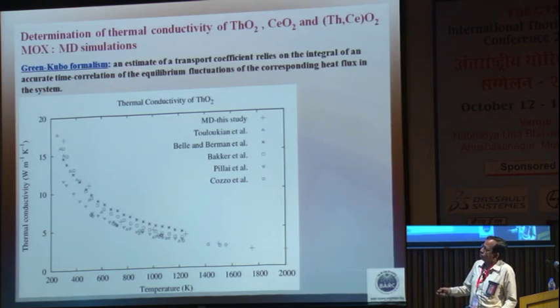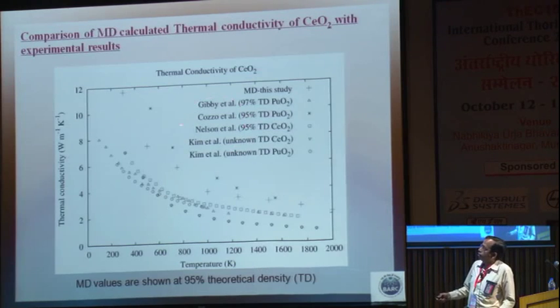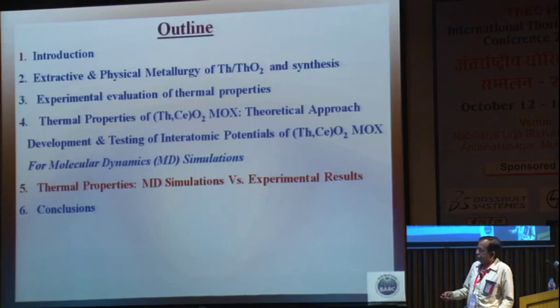So, with that assumption the MD calculations have been done and this is the thermal conductivity as a function of temperature, and here also plotted are the values obtained by other researchers in this area, and the agreement is reasonably good. This is for thoria, and this set of values is for CeO2 as done by molecular dynamics as well as by experiments done by others, and here again the agreement is shown to be quite good.